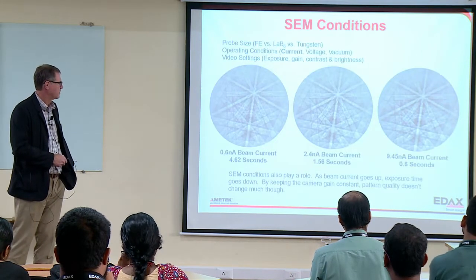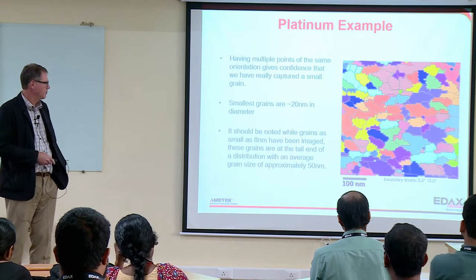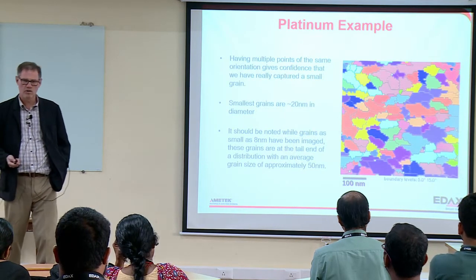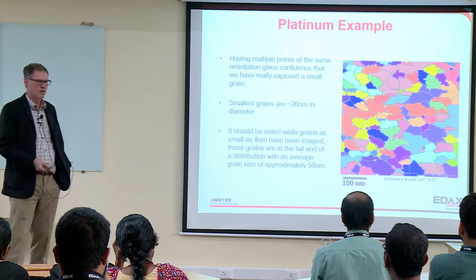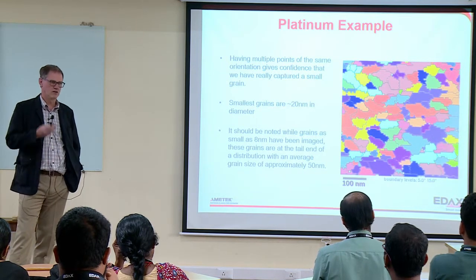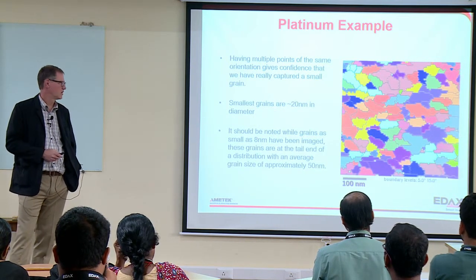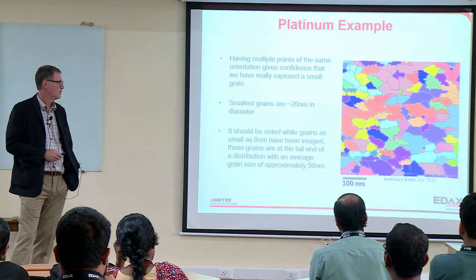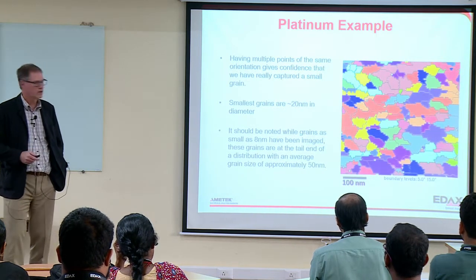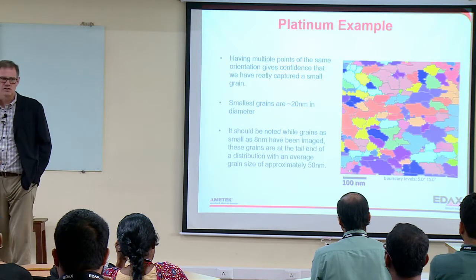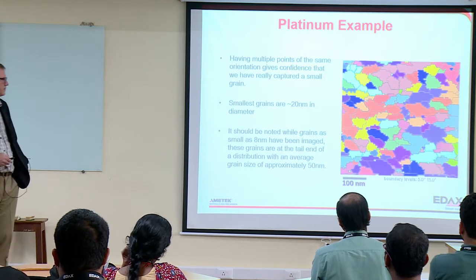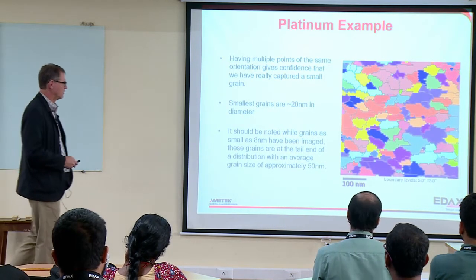Usually what I tell people is anything bigger than a micron is pretty straightforward. As we start to drop below a micron and down into the 20, 30 nanometers, below 50 nanometers, it gets to be a little bit more difficult. And a lot can be done, and I'll talk later about TKD, which is a technique we use to try to overcome some of the spatial resolution issues.